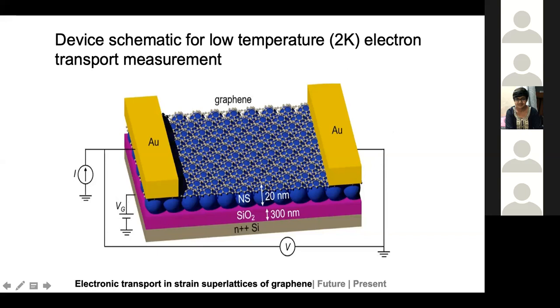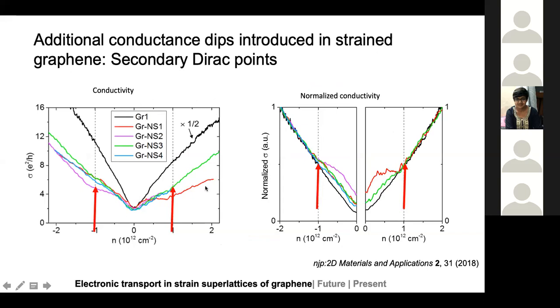So this is what the conductance curves look like. Let's look at this curve on the left first. You have conductance, or conductivity, on your y-axis. The x-axis shows the number of charge carriers, which again is tuned by the gate voltage. This black curve corresponds to flat graphene, which is on a flat surface, no nanospheres present, hence not much strain present. And that looks pretty similar to what you have for normal graphene, as we discussed earlier.